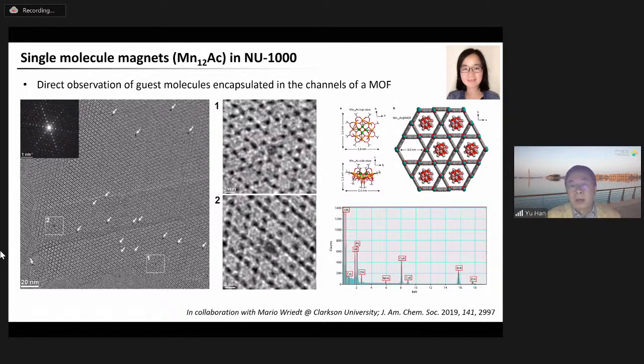So we collaborated with Mario's group at Clarkson University, who immobilized single molecule magnets into a MOF called NU-1000. Based on the size of the guest molecules, they predicted that this magnetic cluster should be located in the primary hexagonal channels because their size is larger than the secondary triangular channels. This is their prediction. Well, our HRTEM observations confirm that this is indeed the case. As you can see from the image, discrete black dots are widely distributed in the MOF matrix. If you zoom in, you will see each black dot precisely resides in the hexagonal channels.